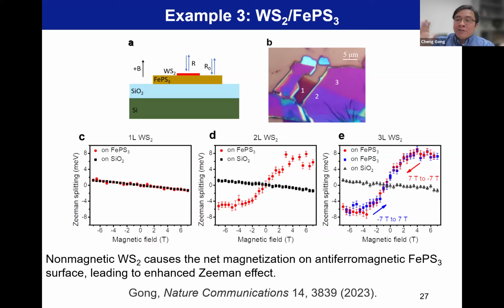Initially, they are identical. So there's no difference between this left and right circular polarizer absorption dip. There's no difference between spin up and spin down band gap in tungsten sulfide. And when tungsten sulfide is put on iron phosphor sulfide, which is anti-ferromagnetic material, naively speaking, we should expect it's just like on silicon oxide. When you change the magnetic field, you should just see a normal Zeeman effect.